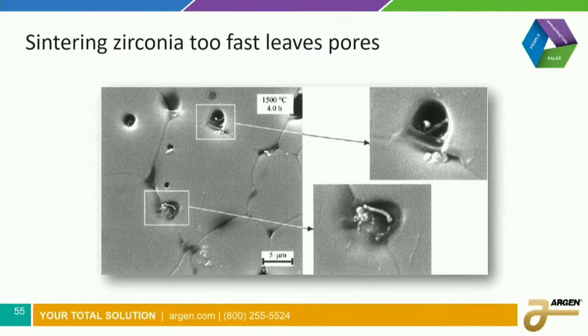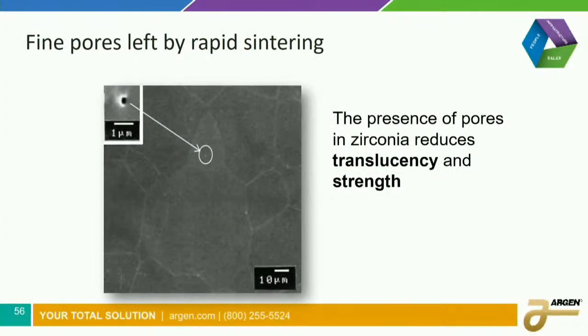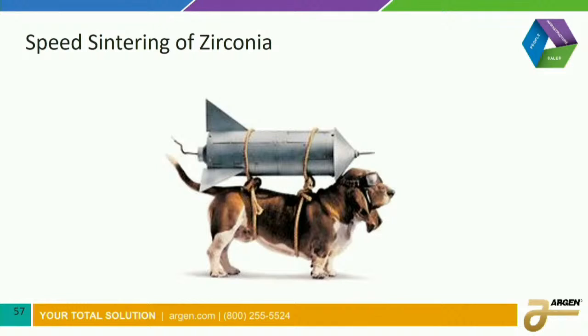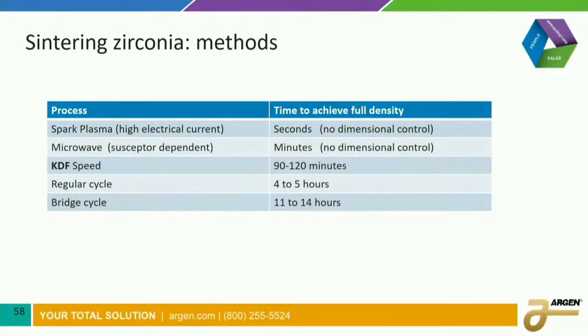So, if you do it traditionally and just try and move the furnace faster, what happens is you leave pores behind. You see this, the grain boundary just sweeps away the oxygen or the air, and if you go a little too fast, then you're going to leave these little holes behind, and these reduce your translucency as well as your strength. So we need to make something work the way it wasn't designed to work. Here we have a nice old basset hound with a rocket on it. So how do we do that?